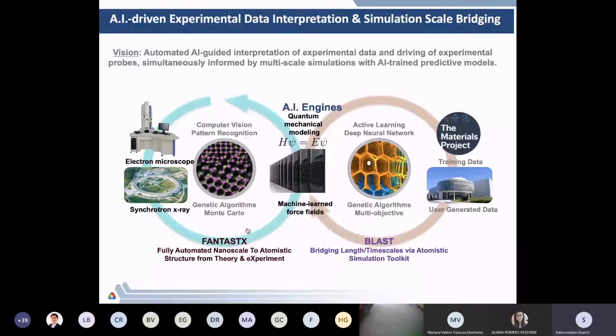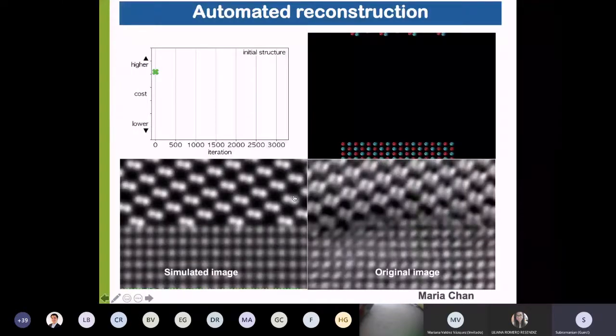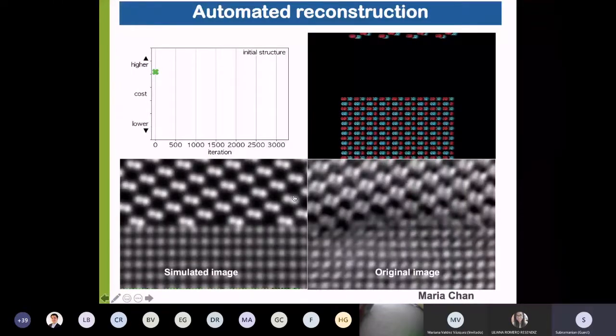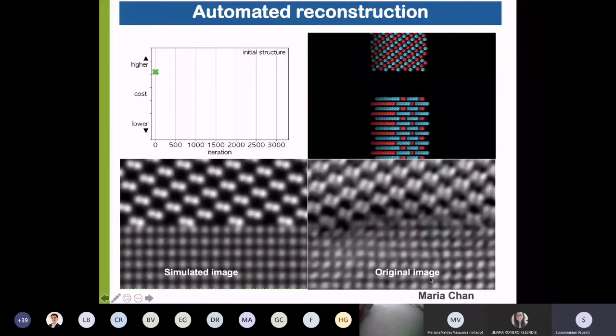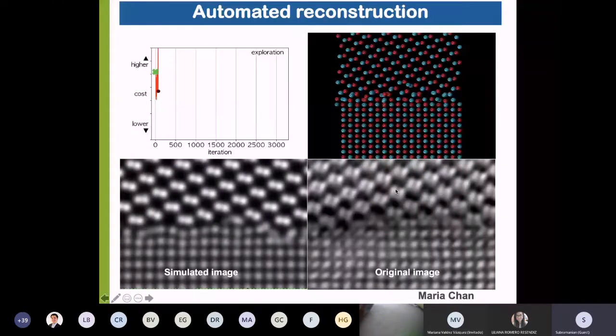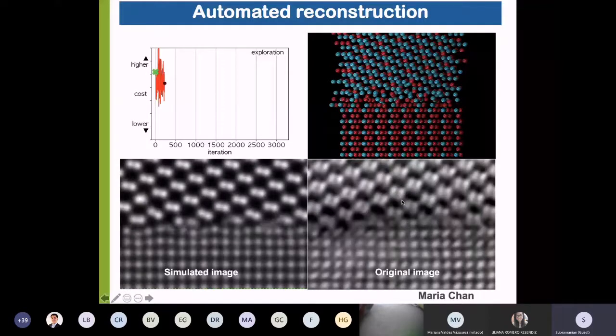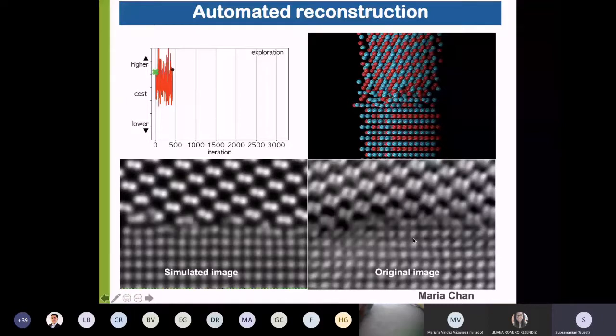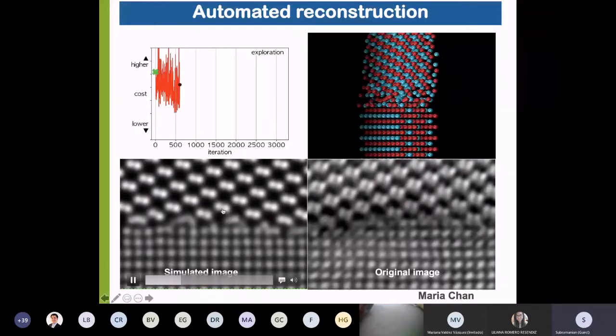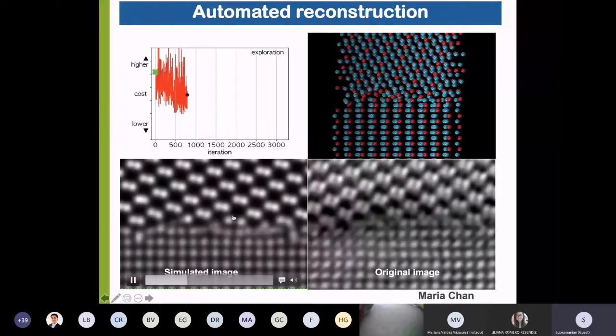So what we are doing, along with my colleague Maria Chan, who's developing Fantastics, is to combine information coming in from the BLAST framework. And so you have now physics-based information that is used along with computer vision to basically do better in spatiotemporal resolution. And I will give you an example from my colleague, Maria Chan. Basically, this is a typical microscopy image that you obtain for a cadmium telluride interface. And what you're doing is now synthetically generating different interfaces, and you're trying to actually use computer vision to match the images and come up with atomic locations.